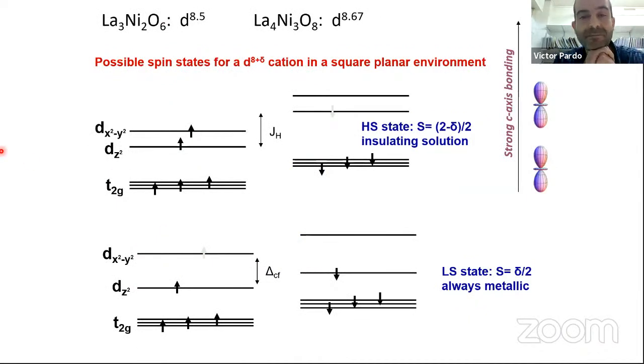So in order to understand it, we need to add an additional ingredient that we don't have in the cuprates. In the cuprates, copper 2+ is a low spin state. There's no problem with that. But with the nickelates, when you start filling the eg shell, you can do it in two ways, and these compete in energy. So this is an additional ingredient that you don't have in the cuprates. It could be that the crystal field is big, and you have what is called a low spin state because you start filling up spin, down spin, and then the up spin again. Or it could be that the crystal field is small, and what's big is the Hund's coupling, so that spins want to be parallel, and then you have a high spin state. So depending on the competition between Hund's coupling and crystal field, you could have low spin or high spin solutions.